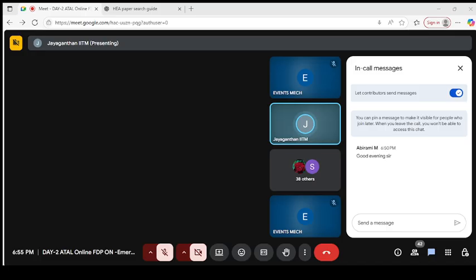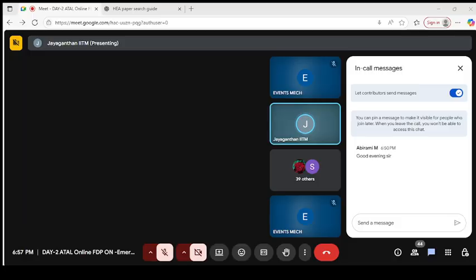This I call microstructural engineering of the material: the as-fabricated sample, followed by post processing, and we can control the microstructure. Obviously, when you give heat treatment, the microstructure will undergo transformation. This we call phase transformations actually. So it's possible to tune the microstructure. As a result, we'll be able to end up getting the desired microstructure to give record properties.